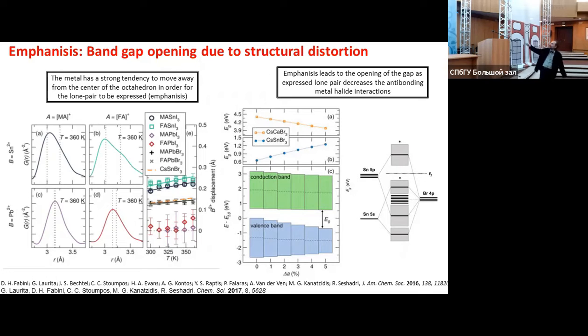And how do we know? There are calculations substituting calcium with tin. Calcium doesn't have this contribution, tin has it. And you see that clearly there is a significant change in the trend of the valence band. And by applying pressure or deformation, this is an effect of the temperature based on thermal expansion.